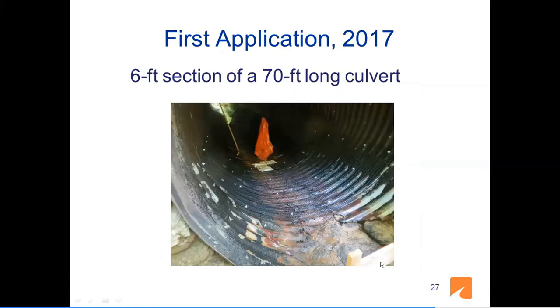Our first application was last year in 2017. In the summer, we fixed a 6-foot section of a 70-foot long culvert. As you see, this is the bottom of the culvert, the invert of the culvert. And if you look carefully, this culvert was coated with asphalt, but it was still corroding because of abrasion, and corrosion was occurring. So we asked them to remove this asphalt coating so that it would bond better with our material. Then they said they would rather replace the culvert rather than take that coating off. It was not an easy job to take that coating off.